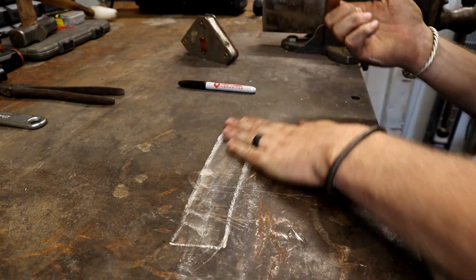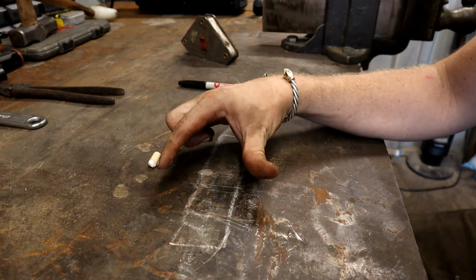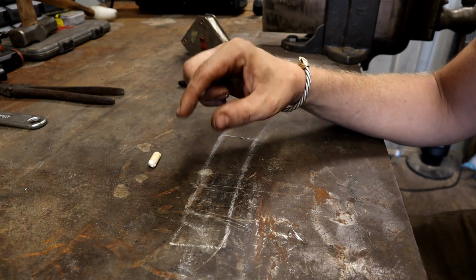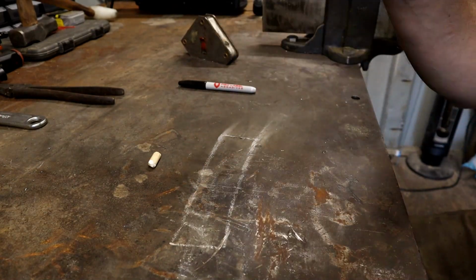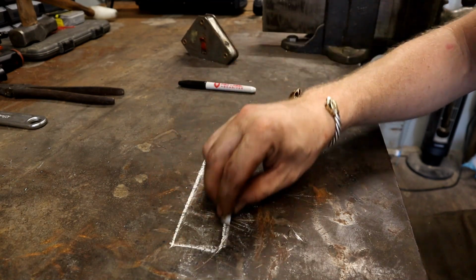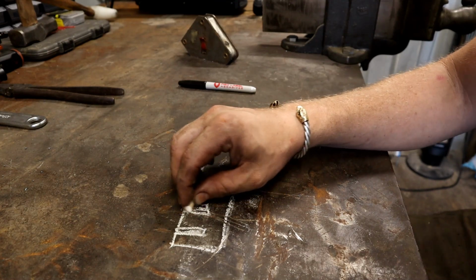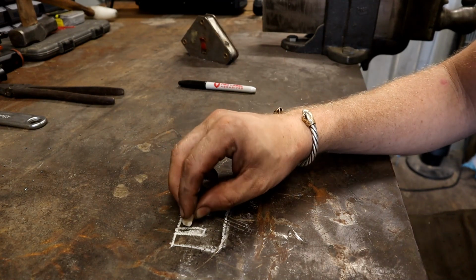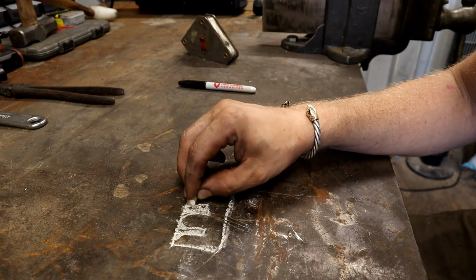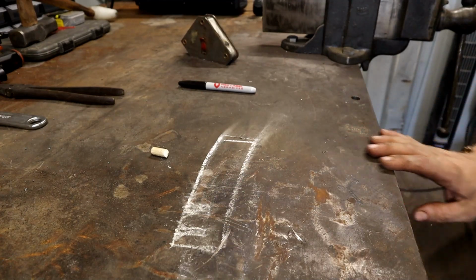The very last thing you want to happen with ladder, you really want your materials to compress this way so that you have more layers showing in some areas and less layers showing in other areas that you would cut away. So we did learn some things. Do your ladders, try to make your grooves, at the very least, when you do these straight cut-ins like this, come in and round the very little bits of these corners over just a little bit, and it will save you so much time and produce much better patterns.